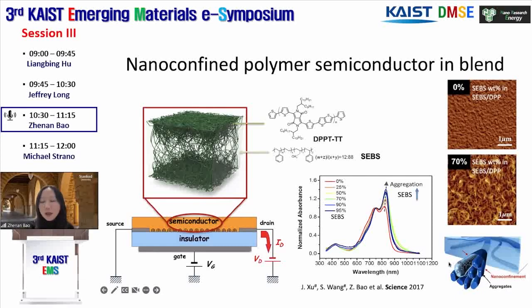So basically, using additional advanced X-ray characterization, we determined that in this nano-confined structure, the polymer is forced into a more planar conformation and reduces the conformational disorder. And this is key to much improved charge transport.